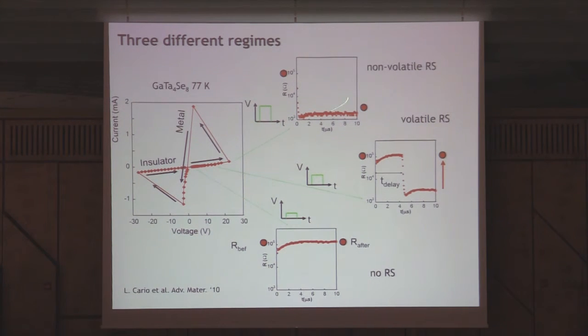So this means, this is what I showed you before, is you apply a very strong field, a very strong electric pulse, and you can change the initial resistance very quickly to a value that remains low. So this is a non-volatile change. If your pulse is very small, of course, you do nothing to the system. You start with high resistance, and you remain with high resistance.